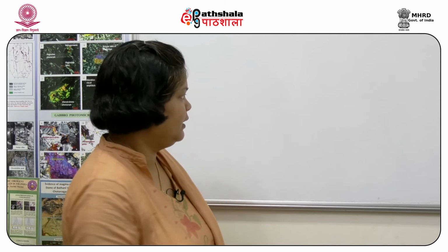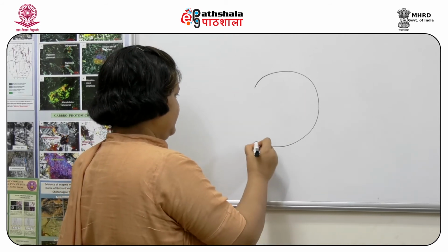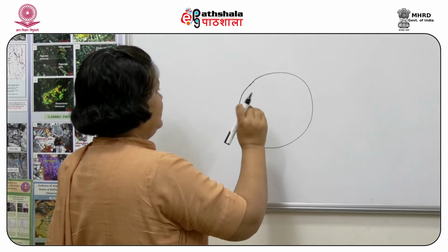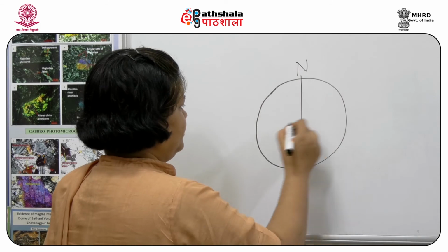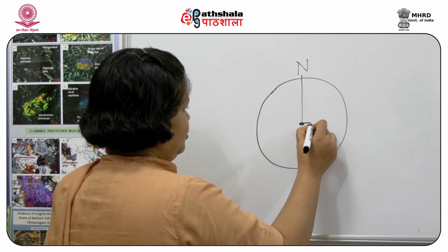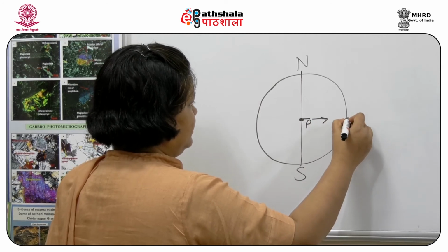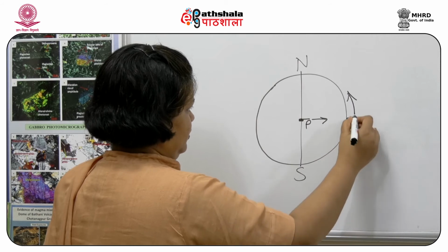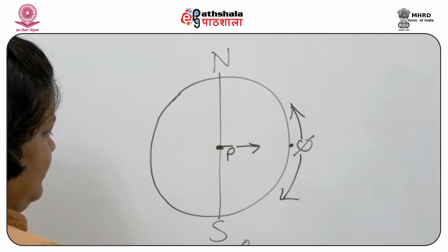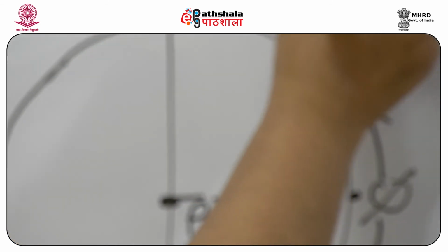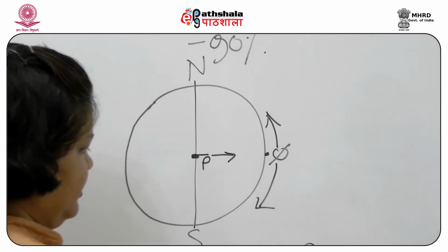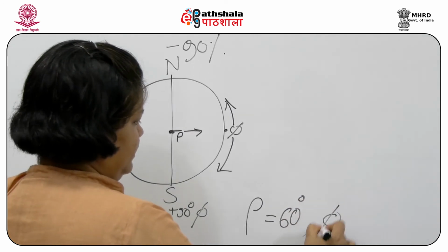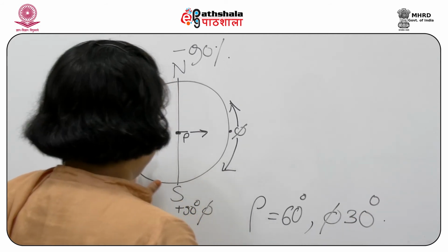Now I will illustrate the use of a stereo net, or what we call a Wulff net. What we have here is a Wulff net, a primitive circle which we observed in the stereographic projection. We have marked here the south pole and the north pole. The rho angle is measured from this point outwards, and the phi angle is measured either this way or this way, here being plus 90 degrees phi, and here being minus 90 degrees phi. So if I have to plot a plane which has a rho of 60 degrees and a phi angle of 30 degrees, the first step is to take the